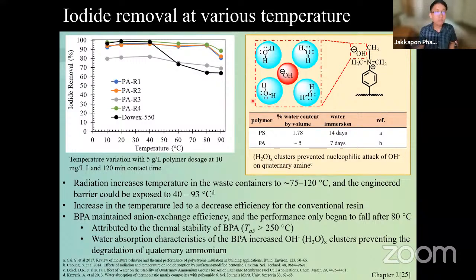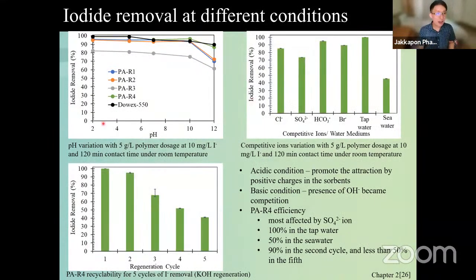And I also studied the pH variations from 2 to 12. It's quite good. At high pH, you have more and more OH minus in the water. That's why it goes down a little bit. But for competitive ions, we have the seawater here as well, and it can be used to about 40% in the seawater environment. And I did the regeneration cycle 5 times.